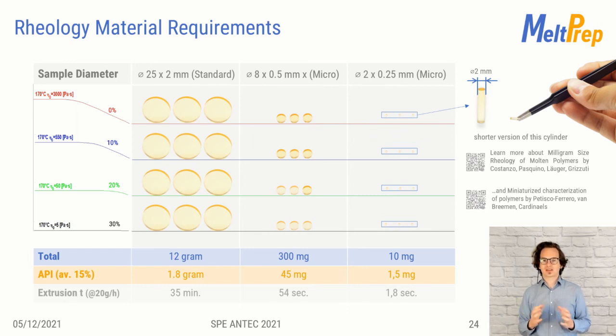Imagine operating an extruder at the lowest throughput that you can find, let's say 20 grams per hour. You have less than a minute to find the operating parameters before you wasted more material than you would need for rheology. If this is still too much for you, even smaller sample sizes are available, but they also require experienced rheologists to perform the measurements. 10 milligram of the material required equals an extrusion time of a few seconds only.